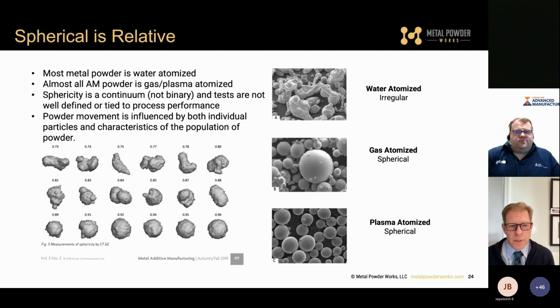And when we look at sphericity measurements, it starts to become very hard to tell why a 0.8 sphericity measurement is so much different than a 0.89 or a 0.9 sphericity measurement. So, things aren't always what they seem. Not all materials form nice spheres in an atomizing environment. If you look at aluminum atomizing, for example, it tends not to form the nice spheres that Inconel or nickel or titanium do. So all of these things play a factor.